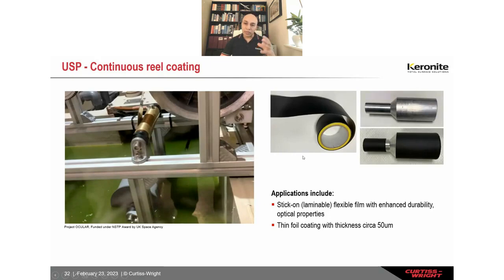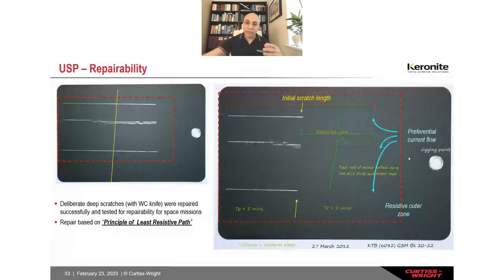And the idea is, rather than having to coat a component, we coat this, for example, with a black coating, chop it off with the scissors, and then we stick it on a laminable, flexible film. That's exactly what we did. We cut it, and we wrapped it around those cylindrical surfaces to make them black. And for example, you can see, you can flick this black coating. This is under tension, and it's not coming off. So you can literally wrap it around a part, right? So it is still highly flexible.